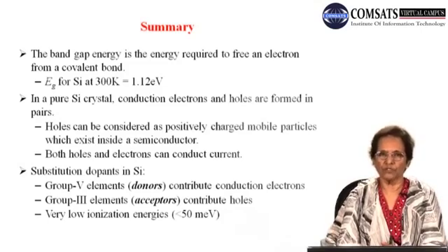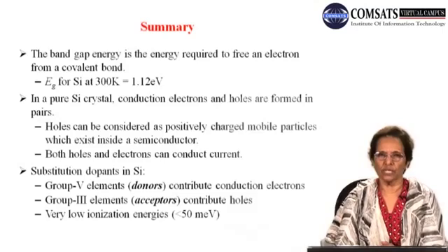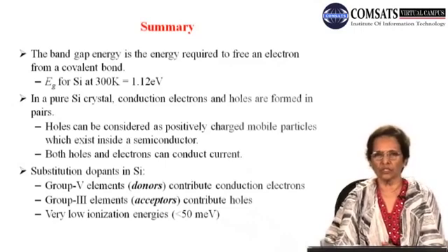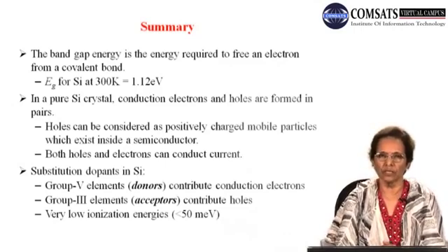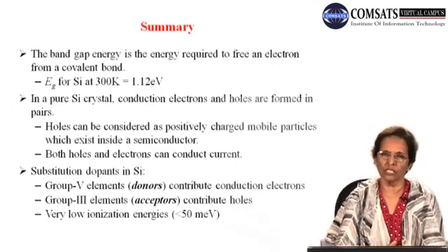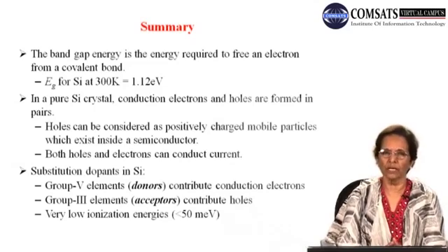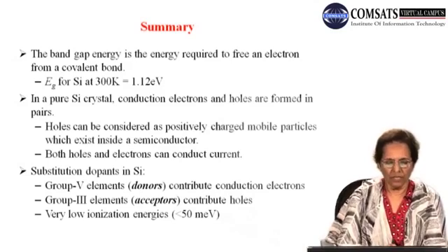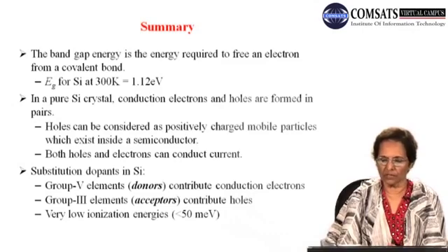So at room temperature there is a finite concentration of electrons and holes present in silicon, and this concentration is approximately 10 to the power 10 per cubic centimeter, even though a large number, yet not so significant in terms of the crystal atoms present in the host crystal. Then we summarize that in pure silicon crystal, conduction electrons and holes are formed in pairs, as I just said, coming from the thermal generation process.